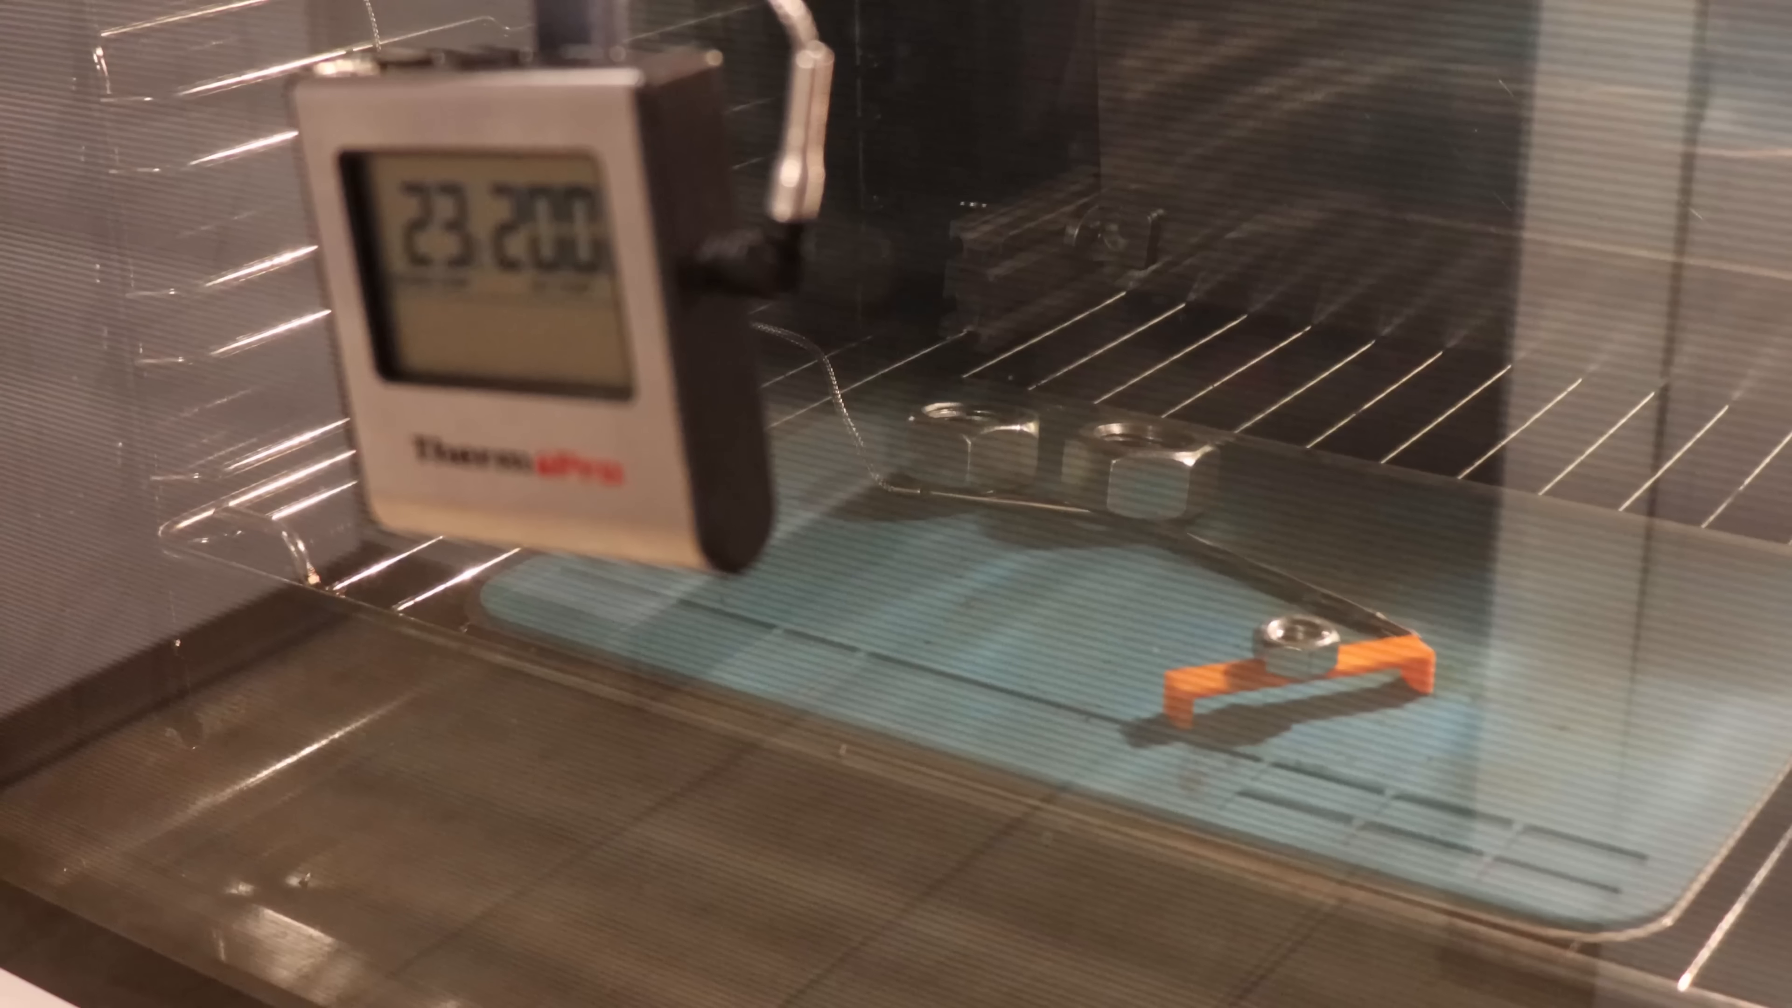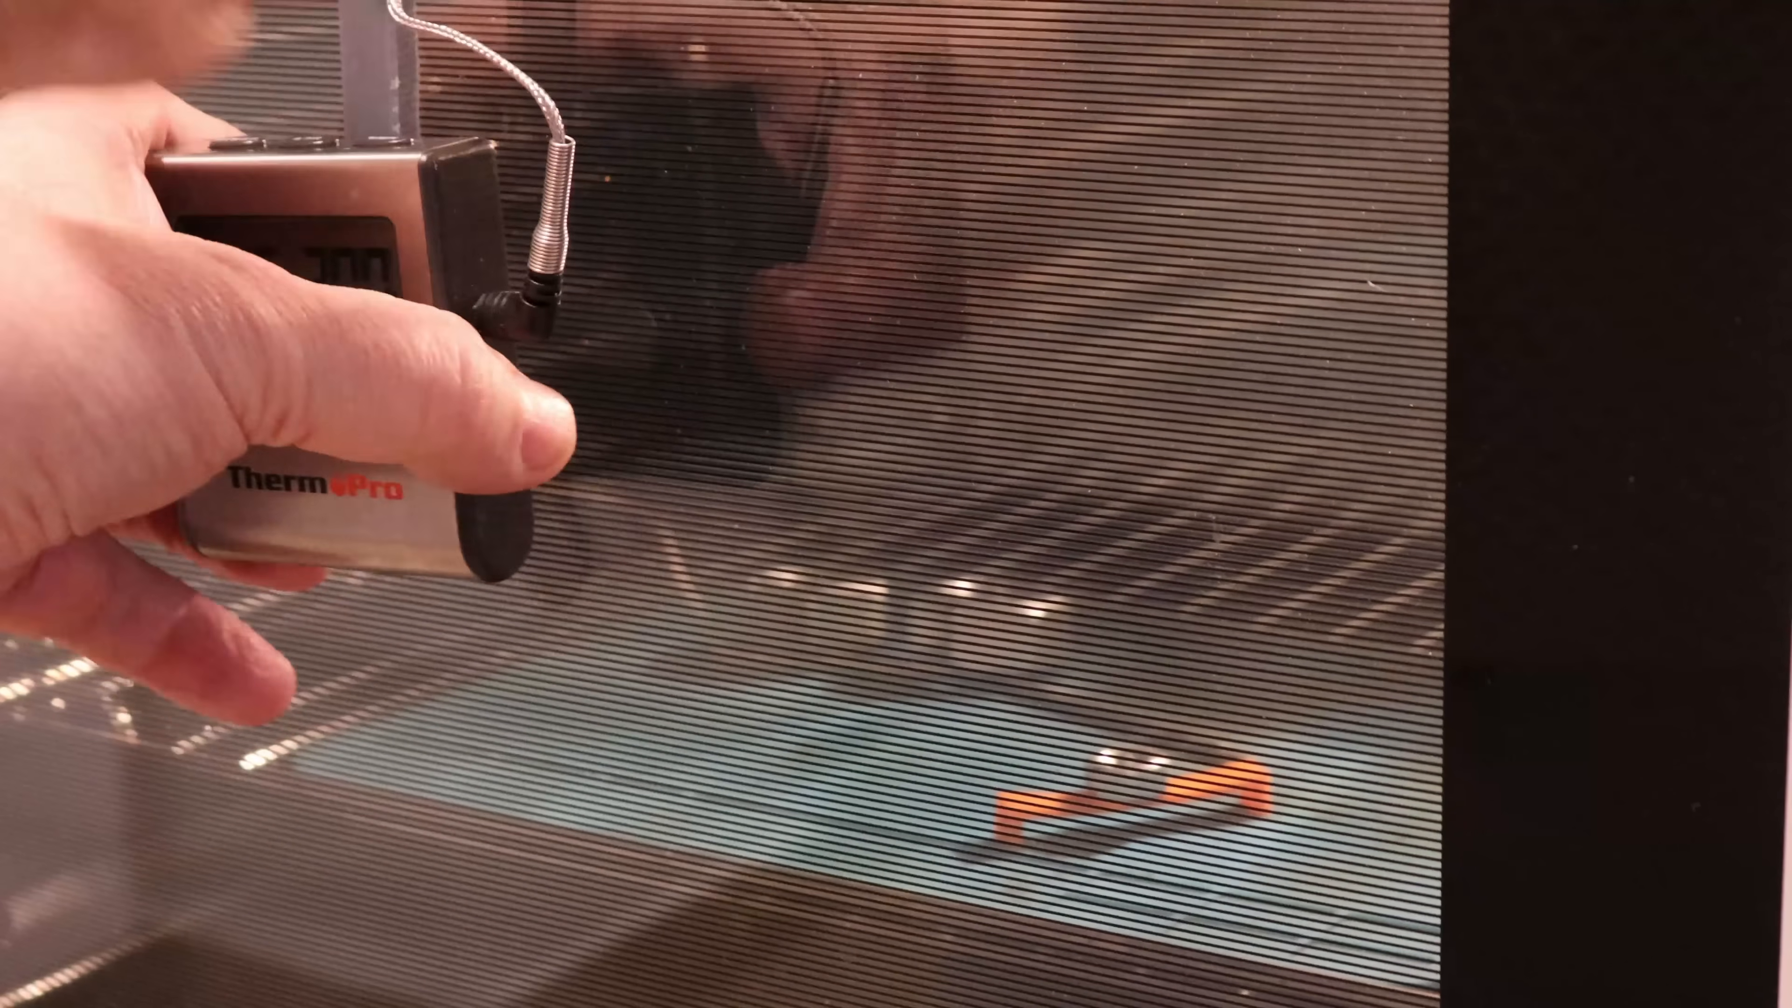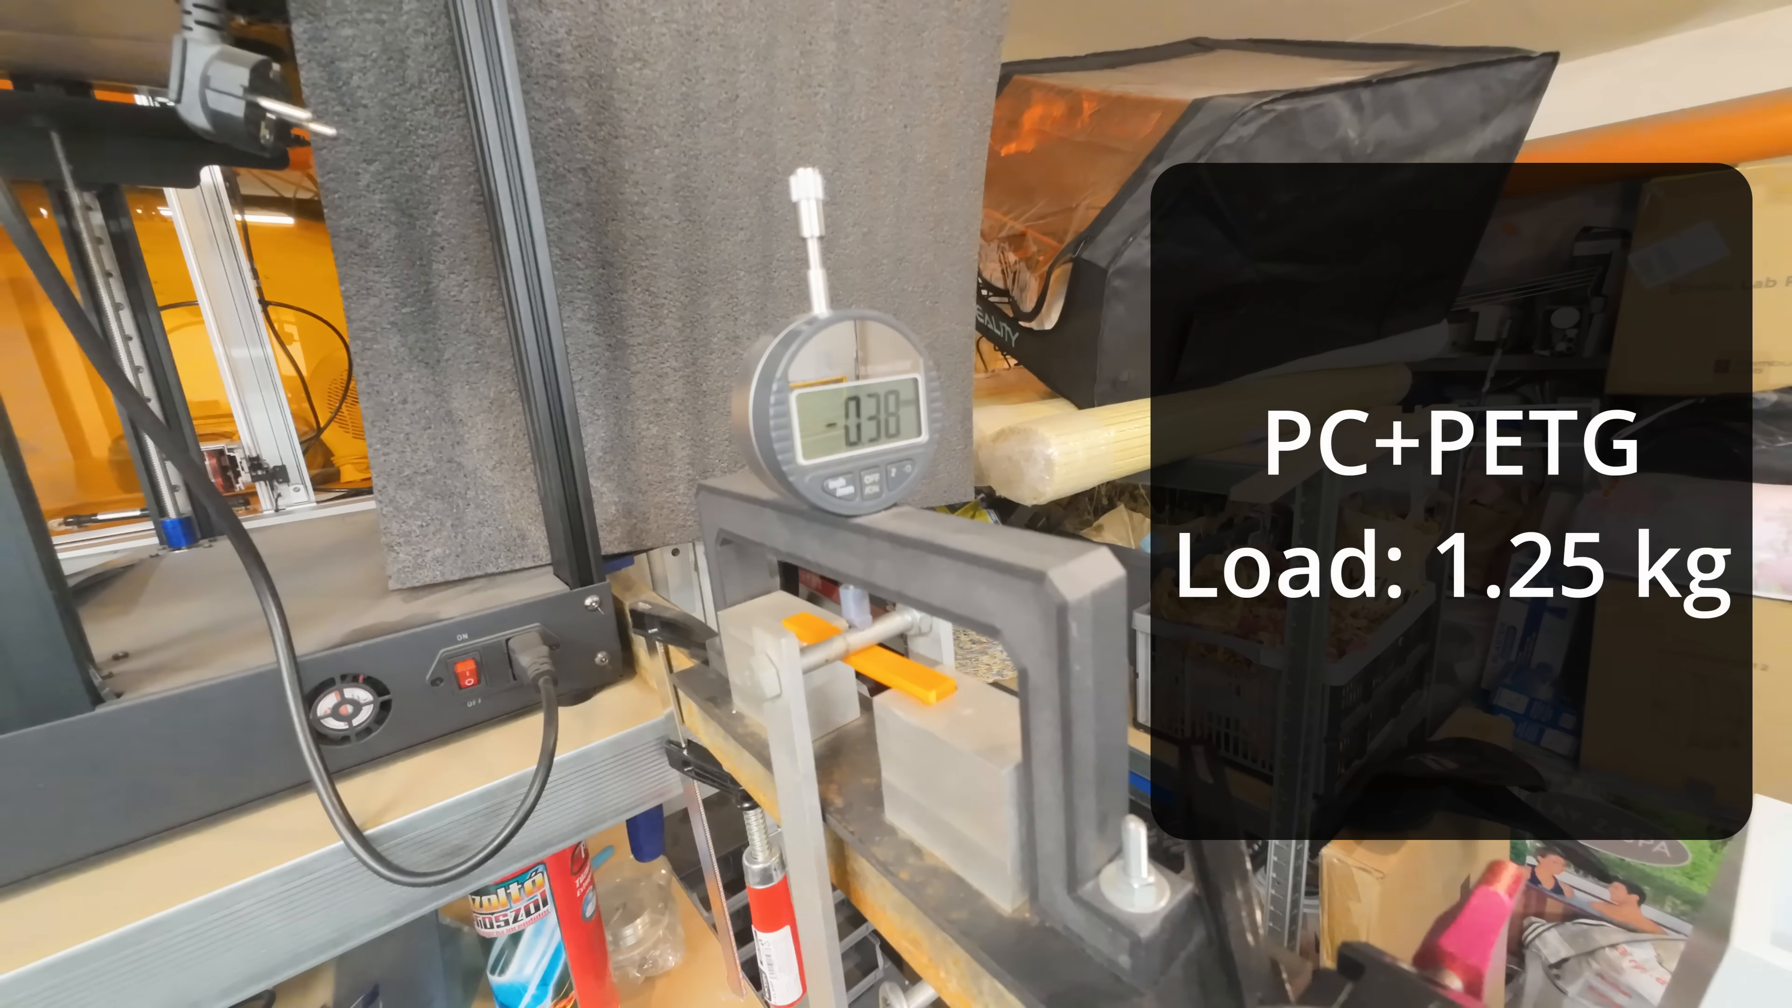Temperature test in the oven, where I want to record the temperature on the first noticeable deformation. M10 nut as a small load. And this is sped up timelapse video. And the first deformation I noticed at 122 degrees Celsius. At 136 I stopped the experiment. I want to see how flexible is the material. And of course it is soft and flexible now. This test doesn't follow any standard, but I am repeating the same testing method, and this number is very similar to the average polycarbonate.